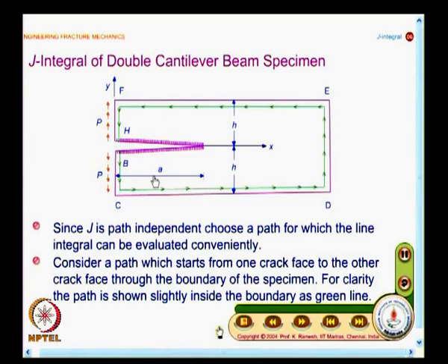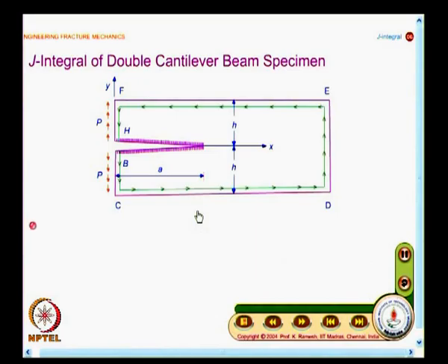See, even before we look at the discussion, you can easily say that whatever happens on the faces CD, DE and EF, the line integral will go to 0. We have to calculate the line integral only for the segments FH and BC. I have already given you the reason that you are looking at a free surface, we would formalize it.